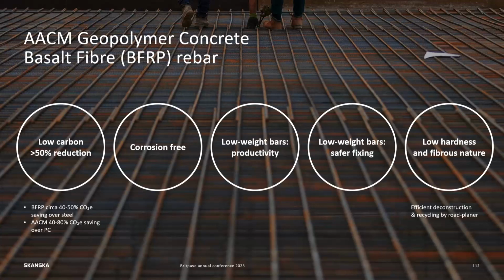And I just briefly look at the low hardness, that fibrous nature of the basalt fibre bar. Part of the M42 trial was to deconstruct the slabs that we've constructed using a conventional road planer. Basalt was a rock. Basalt fibre reinforcement has come from being a rock. The intention was to plane the concrete road up and create a 6F2 material for using elsewhere on the project, or perhaps for sale and transportation elsewhere as a 6F5. But actually creating that material graded through the adjustment of the planer in one move, one action, one process, could be quite significant for the ongoing use of it as a construction material.